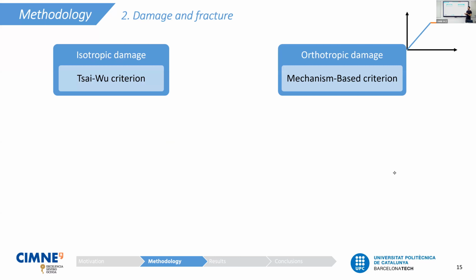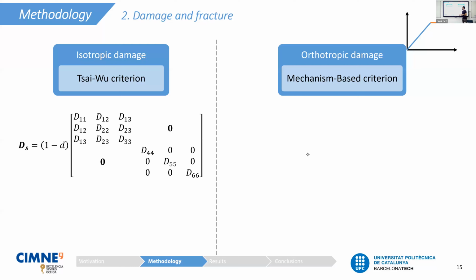Once we have established a threshold in which the material goes from the linear to the nonlinear regime, we have to specify a damage evolution law. How is this damage affecting the stiffness? For the Tsai-Wu criterion, since we have only one parameter, we map this parameter using an isotropic damage model, meaning that we are mapping our stress factor into a damage variable D that goes from 0 to 1, meaning 0 that the material is not damaged and 1 that the material is fully broken. And this isotropic damage model considers that the damage parameter affects equally all the components in the constitutive tensor.